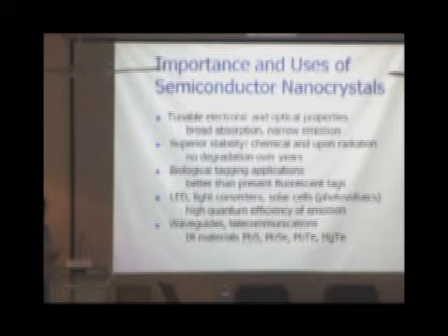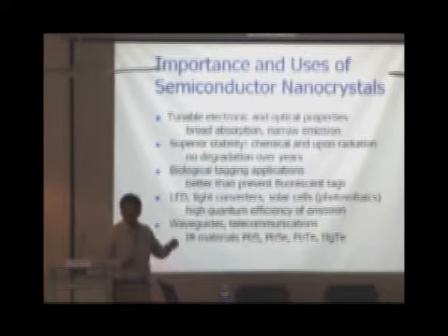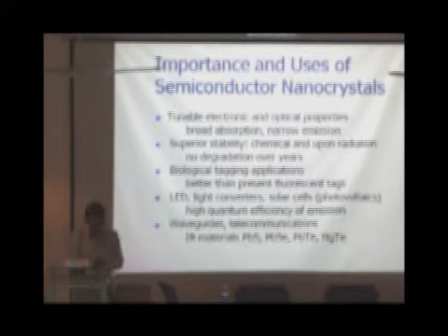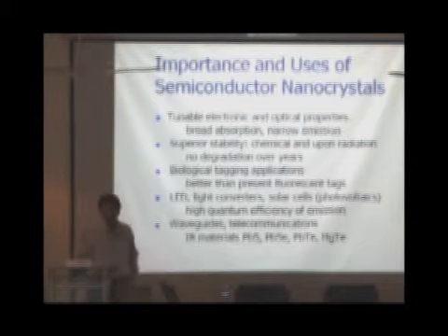They are very good, these particles. When people started research on semiconductor nanocrystals, these were not even stable for hours. But today we can make things that are stable for more than 3 years. They lie in the solution and still shine. The good thing is, compared to dyes which have been used for some of these applications, dyes degrade within 5 minutes of laser irradiation. So you have to reduce the power, which means you get more noise in your data. But nanocrystals don't degrade for weeks. You can continuously shine lasers on them.